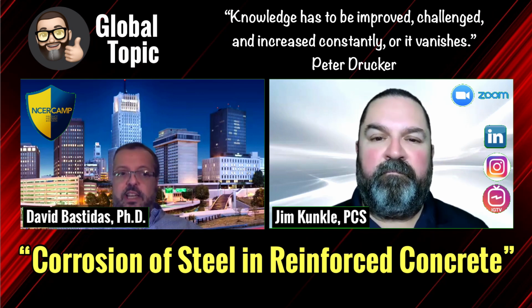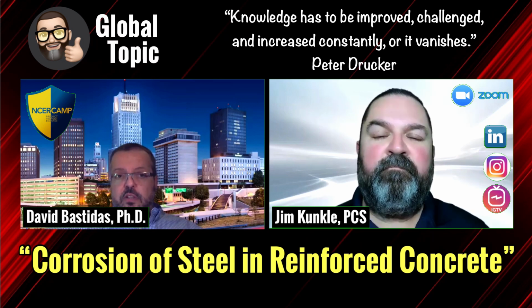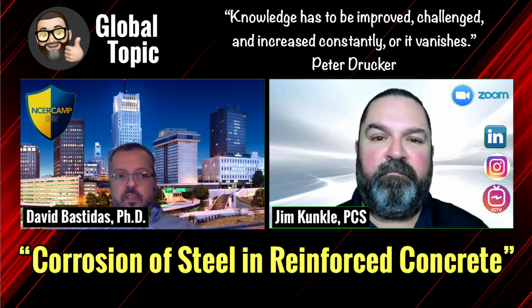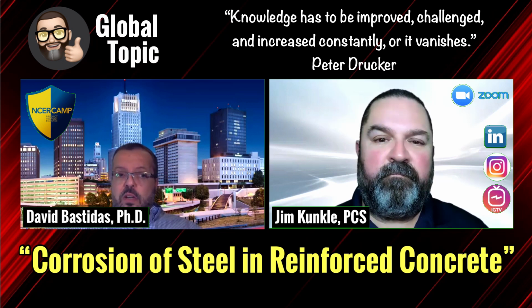We have those containers, those vehicles, and we load them with the corrosion inhibitor. We are using different corrosion inhibitors inside, and the most important thing is that we have found a kind of synergistic effect. It's not just the corrosion inhibitor inside that is protecting, but also the organic nature of this shell is imparting corrosion protection and acting as an oxygen scavenger. So that's one of our main lines on this side of the sciences.